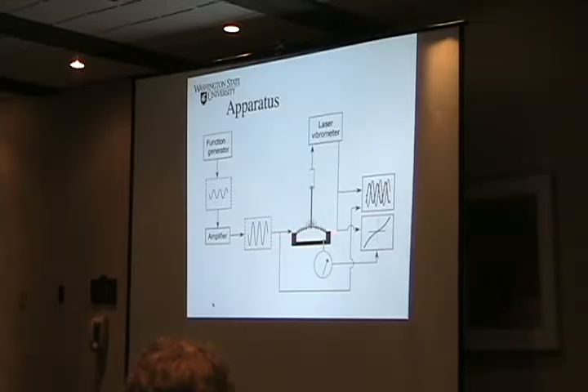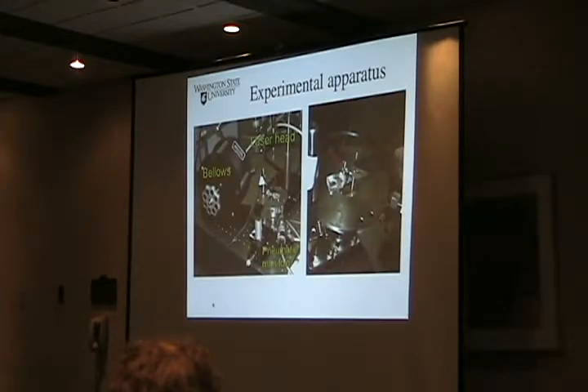So if we strain a membrane to a large displacement, and then we put on a small oscillation either electrically or mechanically, and I'll show you both situations, then measure the resulting displacement and the pressure deflection curve, we should be able to back out what the coupling coefficient is in this system. So of course we do that. We have a small little piezoelectric membrane, stick some probes, start it oscillating.